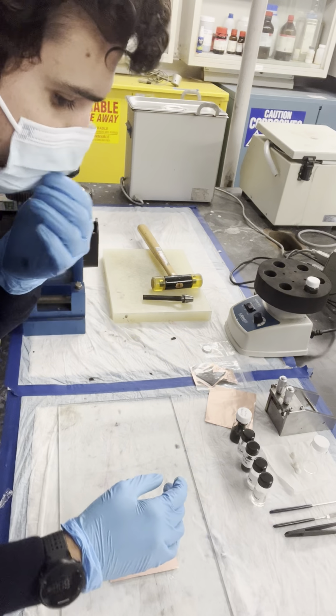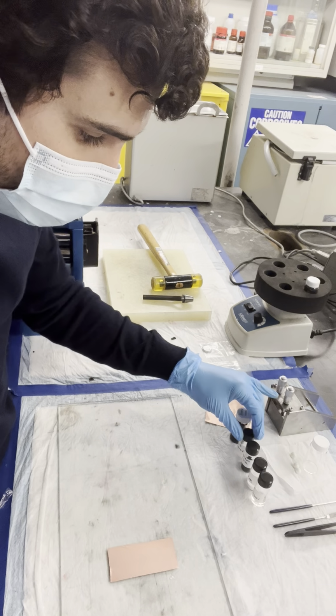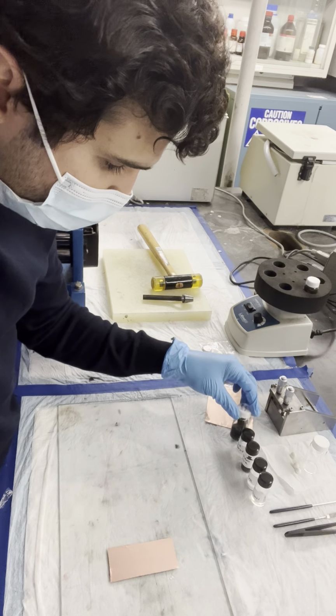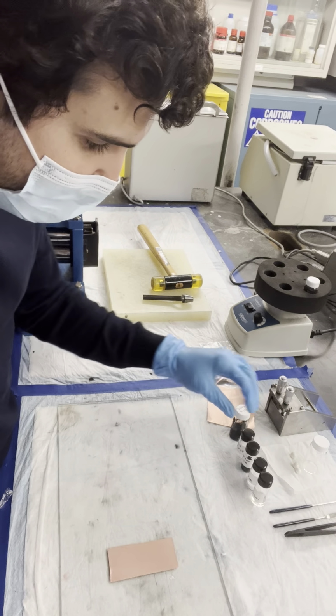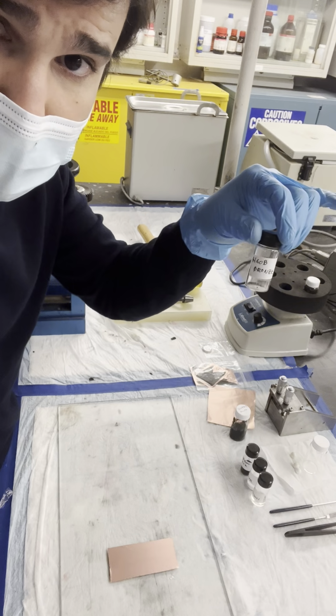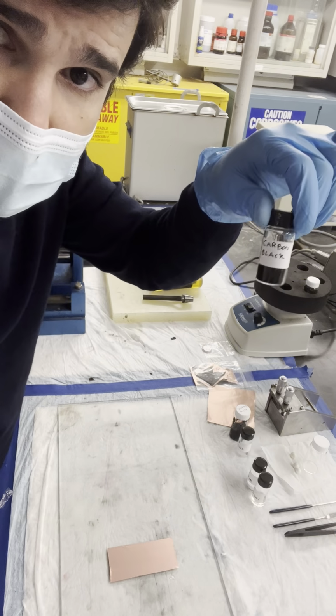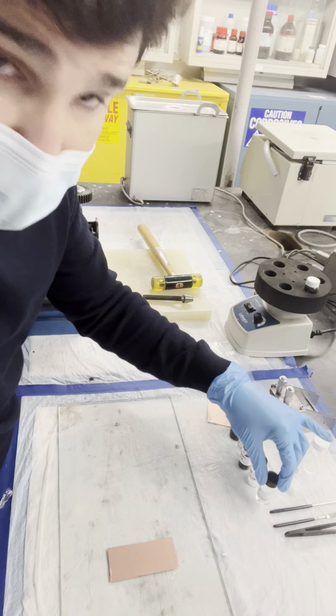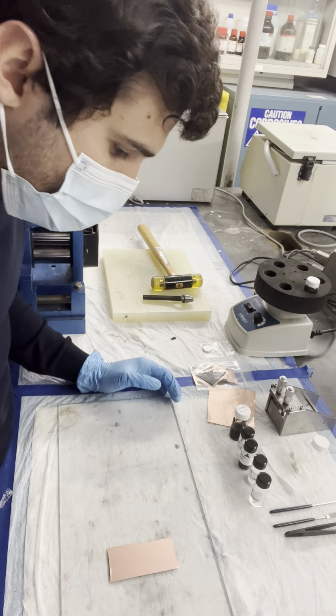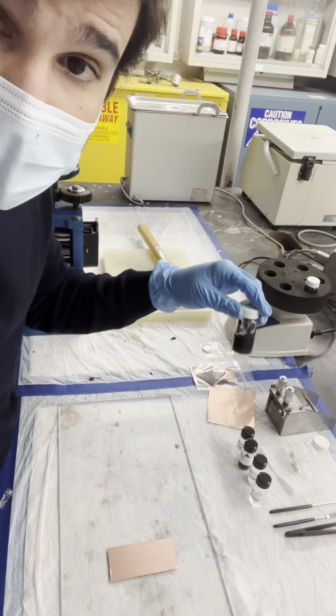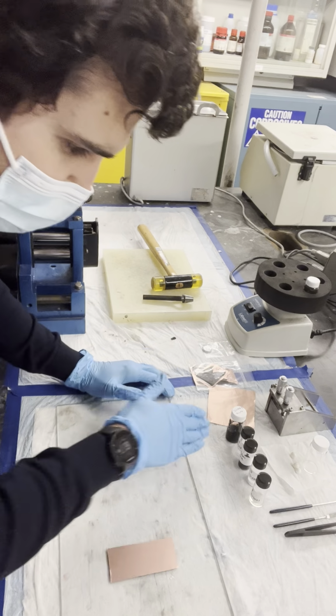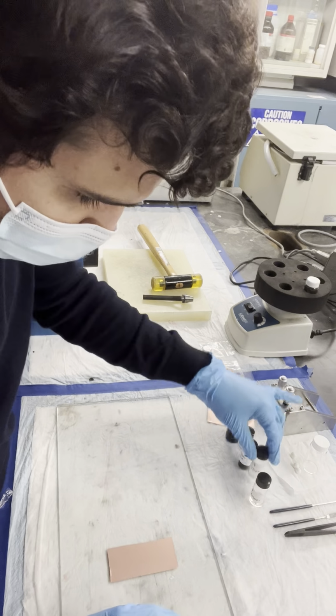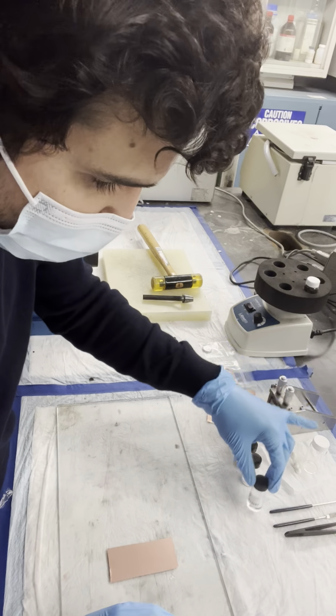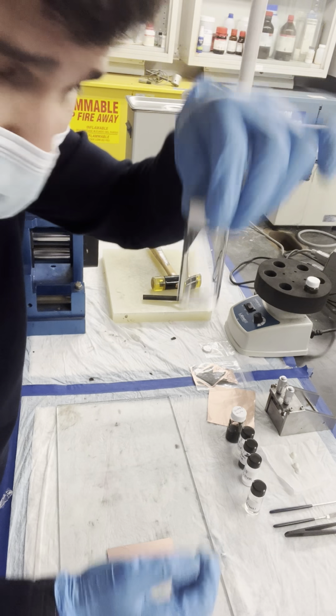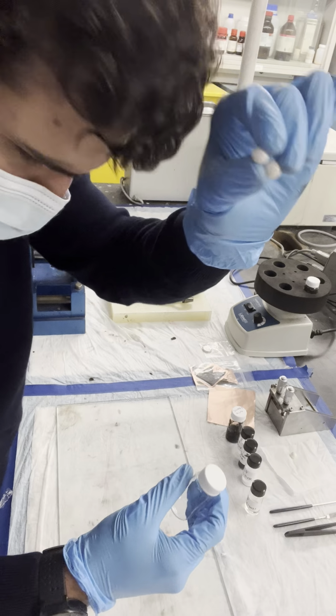So the first step here should be calculating the right amount of each one of them. This amount is very important in a cell preparation, and in this case I used 70% of active material, 20% of carbon black, and 10% of PVDF. The amount of NMP varies depending on the viscosity of the slurry that we want. So after calculating this, we have to dissolve the PVDF into the NMP using just a glass vial like this and some ceramic balls, inert ceramic balls.